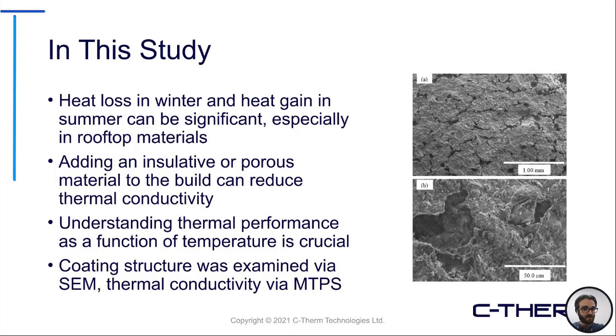In this study as well, it was really important that they understood the thermal performance as a function of temperature. And they were also examining, again, these materials using the MTPS, but we can see some of the SEM images that they were taking to view the structural aspects of their coating on the right here. So we can see that the aerogel coating added this layer on top of the substrate that they were looking to measure.